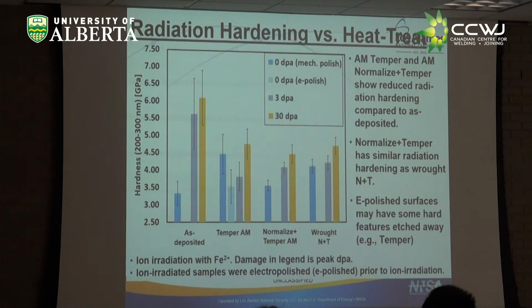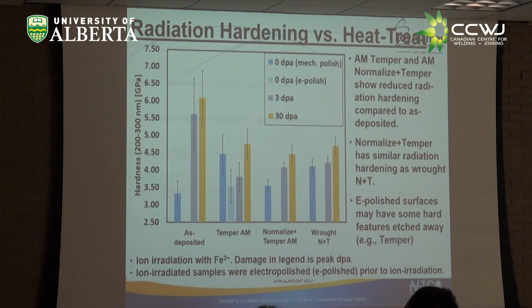So the tempered and the normalized and tempered AM samples showed reduced radiation hardening as compared to the as deposited one. So the as deposited one, I got to go back and look at this again. There's a difference in hardness, and I think he's trying to show here that it's not a difference, it's just absolute. Okay. So the as deposited